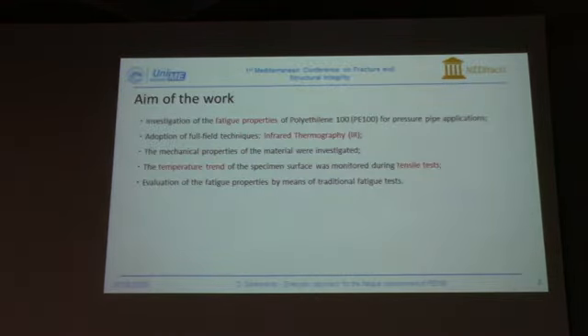So in this work we investigate the fatigue properties of polyethylene 100 for pressure pipe application, and we adopted in this case a non-destructive technique such as infrared thermography. We investigate the mechanical properties of the material, and we analyze the temperature trend of the specimen surface during tensile fatigue tests. In addition, we evaluate in a traditional way the fatigue properties of this material.